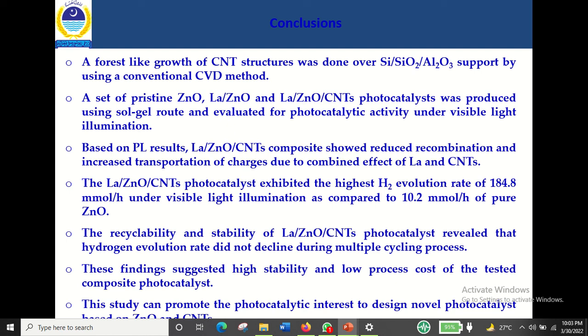The recyclability and stability of the composite photocatalyst revealed that the hydrogen evolution rate did not decline during the multiple cycling process. These findings suggest high stability and low process cost of the tested composite photocatalyst. This study can promote the photocatalytic interest to design novel photocatalysts using the ZnO and